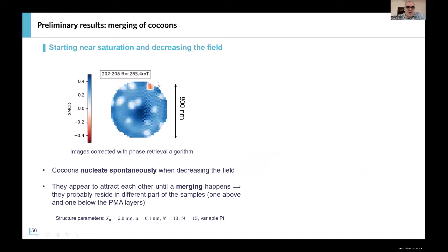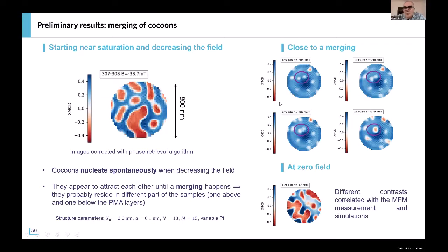You do see clearly, and importantly, we are now sensitive to the whole system because we are in transmission here. So you do see that we have different objects, two different contrasts very clearly. And interestingly, we can also start to have a look at the way these cocoons, that we believe are the ones here, can merge together in order to end up finishing as skyrmion tubes.